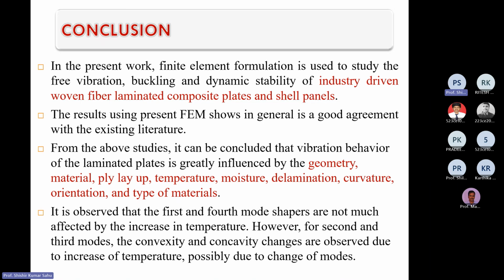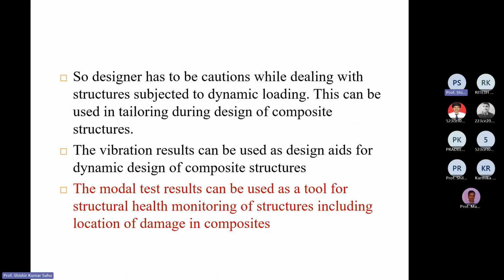So the conclusion: the finite element formulation to study vibration, buckling, and dynamic stability of industry-driven woven fiber laminated composite plates and shells. Result: the present FEM formulation shows good agreement with the existing literature. From the above studies, it can be concluded that vibration behavior of laminated plates is greatly influenced by geometry, material, ply layup, temperature, moisture, delamination, curvature, orientation, and type of materials. So these are parametric conclusions: the effect of different parameters. The designer has to be cautious while dealing with structures subjected to dynamic loading.